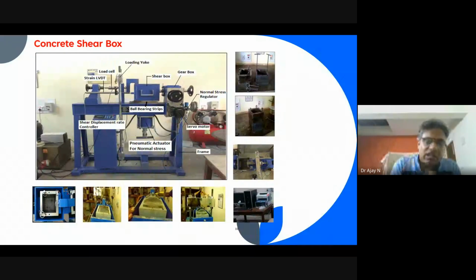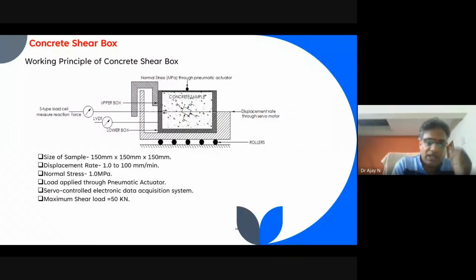the same methodology adapted here, but the size of the cube is 150 by 150 as per the cube standard. We apply normal stress through regulators, and we have a gearbox, and we apply normal stresses through the pneumatic actuator. Everything is completely sensor based, and we measure all these things through the sensors. This was developed in 2009, and later we checked the feasibility of this instrument. That is the main aim of my PhD topic. Here we can apply normal stress up to 1 MPa and a maximum shear load up to 50 kN.